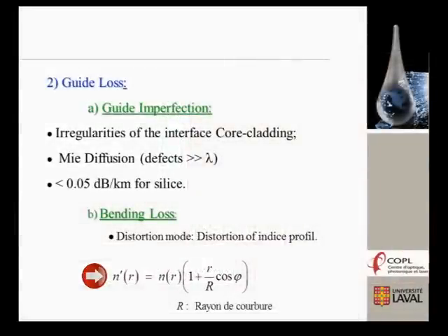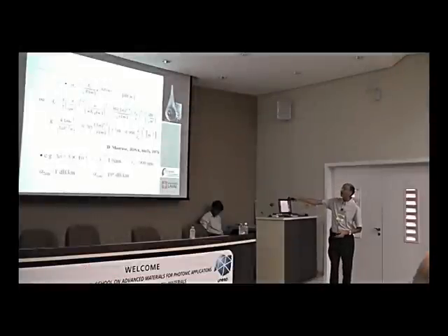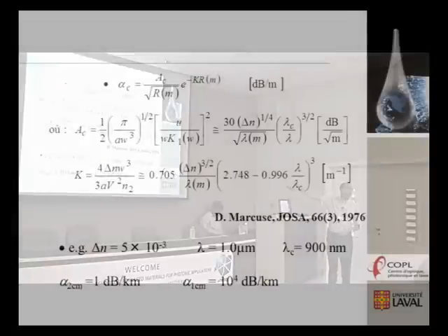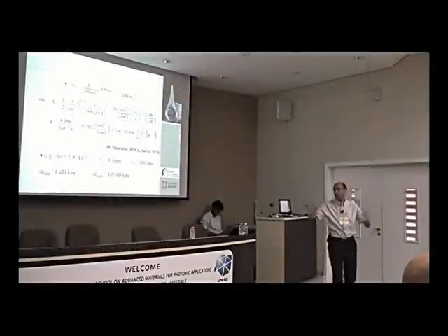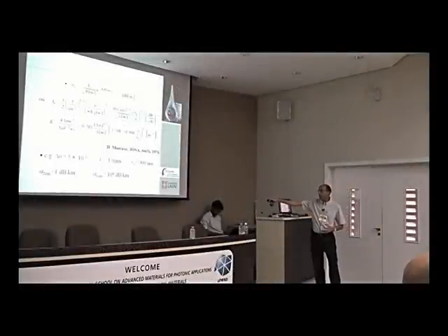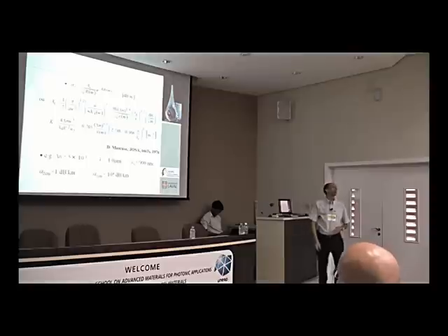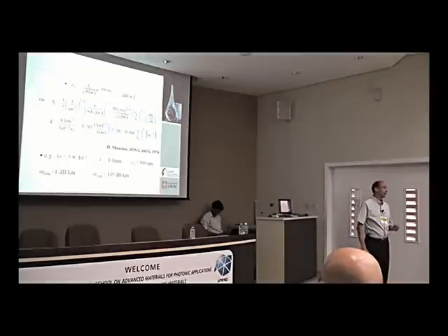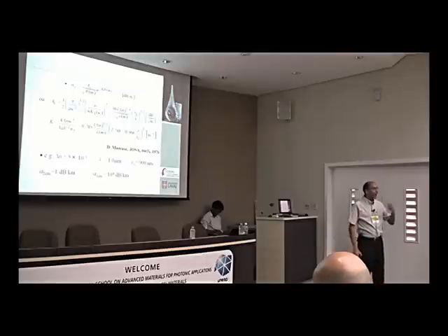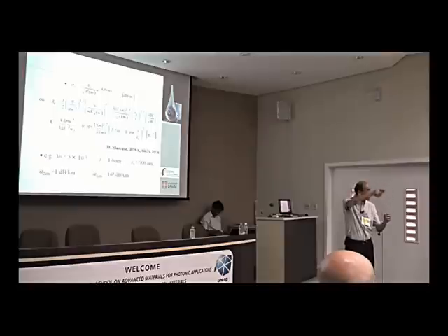And we can measure that. In this paper of Marcuse, he showed these bending losses depend mainly on the radius, and also on two parameters here, lambda c to lambda, and again the fluctuation of the bending. If we measure this parameter, we can measure the bending losses. For 2 centimeters, it's 1 dB per kilometer, but for 1 centimeter, it's something like 10 to the 4 dB per kilometer. It's too high. And this is something independent for us. Because of the bending, we have these losses.